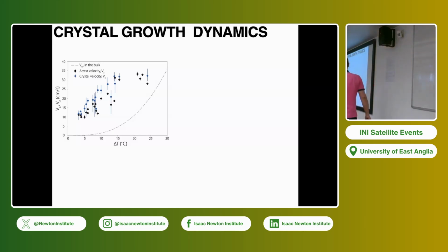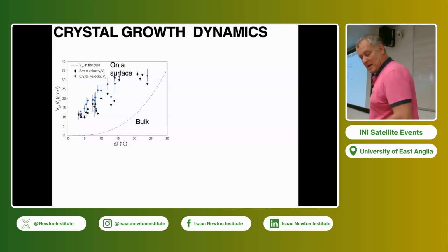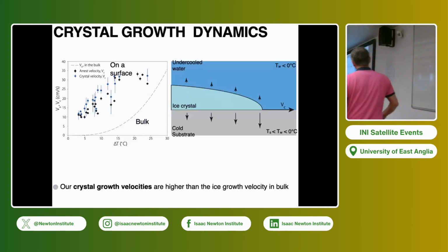What is puzzling, and maybe I will open to this point, is that it's tempting to say this velocity should be the dendrite velocity of an ice crystal growing in undercooled water. If you do that, you should be here. So we definitely have a dendrite that is growing, but the velocity of the dendrite has nothing to do with a free dendrite in an infinite bulk. Actually, it's much faster. But we can understand that easily. The situation we would like to solve is not the dendrite solution that I showed you, but something more difficult, and we haven't found an analytical solution of that. You have somehow a half dendrite that is growing on a substrate.